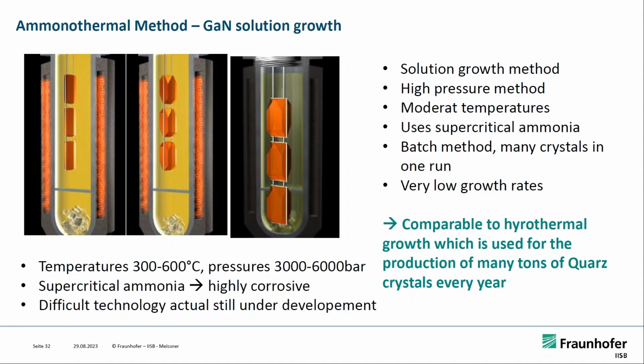The ammonothermal growth process is a solution growth process. It means you dip the crystal seeds into a solution which contains all the material that you want to deposit on the seed. It's like putting a seed in a solution of sugar, and then you grow the sugar crystal. This is very much comparable to hydrothermal growth of quartz.